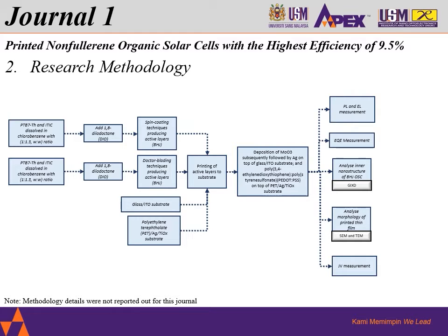And then after that, 1,8-diiodooctane, which is DIO, the solvent additive, is added into the solution over here. And then these were sent into the spin coating technique to produce the active layers. In parallel, the same step was also done, however it was produced with the doctor blading technique. So you can see here, this is actually a comparison that will be reported out later on. The spin coating technique serves as a reference, and what the journal is trying to find out is the doctor blading technique.